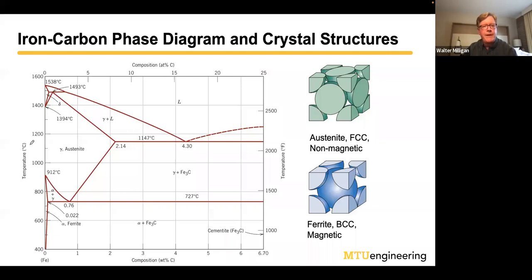So basically this, just like in the case of the water phase diagram, is a diagram that explains what phases are stable at a combination of temperature and composition. Most steels have carbon concentrations less than about 1% by weight. If I take a look in this region down here, I have a two-phase mixture of a phase we're going to call alpha, which has this crystal structure here. It's an ordered crystal, just like ice crystals are, and that's called the body-centered cubic crystal structure.